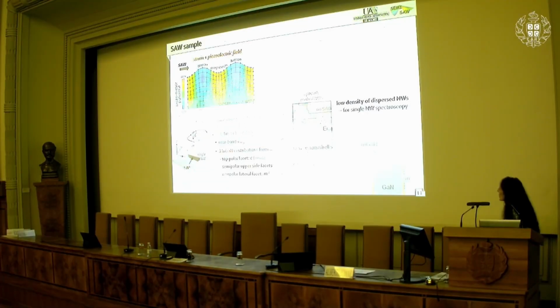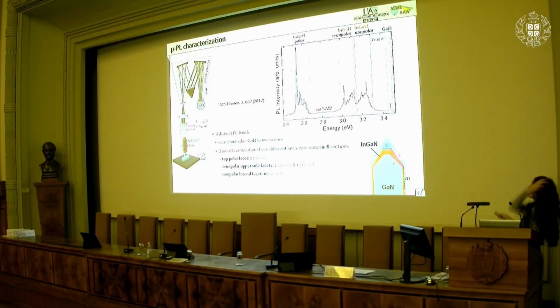As a result, we obtained this spectrum, which is a representative spectrum of the low temperature micro-PL measurements on a single nanowire. And as you can see, there are these four distinct emission bands. This higher energy luminescence is due to the near band edge emission from the gallium nitride nanowire body, whereas these other three bands correspond to different sections, so polar, semi-polar, and non-polar, of the indium gallium nitride nanoshell.